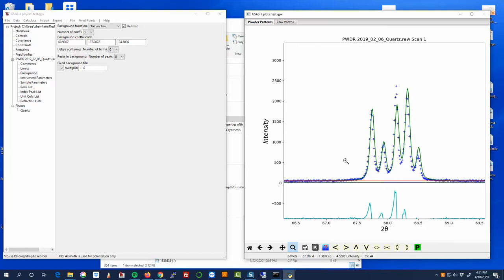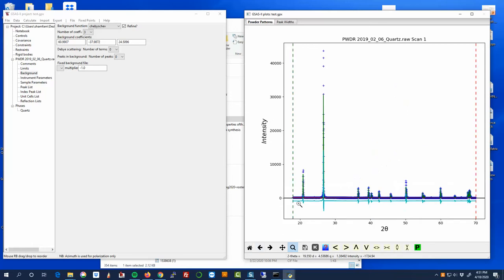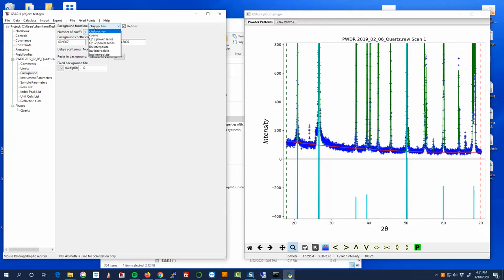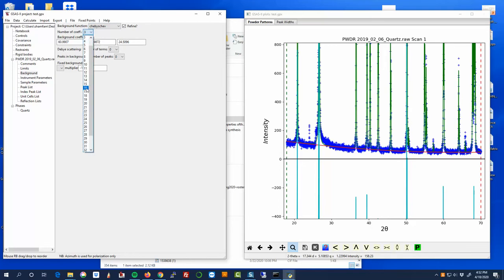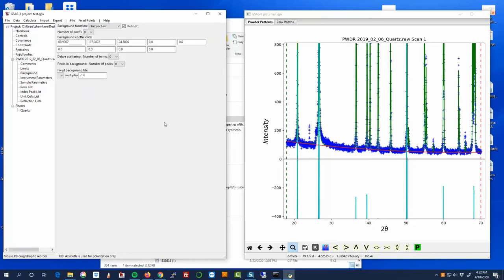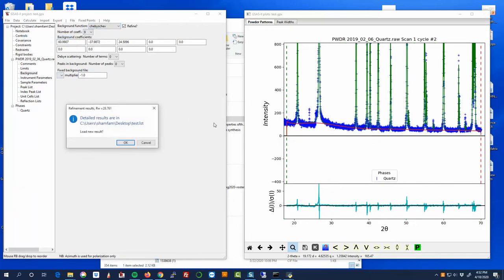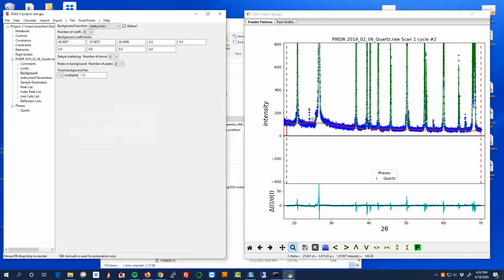The red is the background. And so if I zoom out and I just zoom in very low intensities along this red curve, I can see that that background is doing a pretty good job running through all these blue points in between peaks. Right now, there are different functions that you can fit for the background. And for something like this, it's not going to matter a lot. We can go ahead and add a few additional coefficients. It turns out that the RWP, so this single number that's calculated that describes how good your fit is, it depends an awful lot on how good of a job you're doing fitting your background. So you can get that number lower just by adding more parameters into your background function. So I can say calculate, refine, run again. And you can see that right now it gives us kind of a weird little wiggle here. But that's going to start to go away as I correct the data for the peaks.